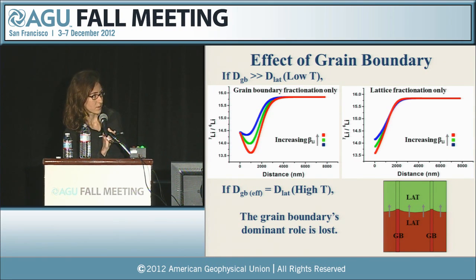And the difference between the 2 graphs is that in the left one, fractionation was only allowed to occur in the grain boundary, whereas in the right one, fractionation was only allowed to occur in the lattice. And once again, from blue to green to red, we have an increasing beta factor. So here you can see that when the grain boundary is allowed to do the fractionating, then the dip that we've been seeing before is produced, whereas when the lattice fractionates only and the grain boundary does not, that's not produced.